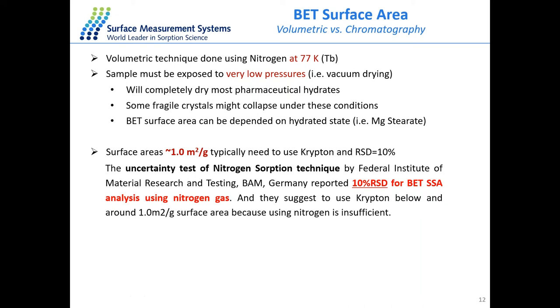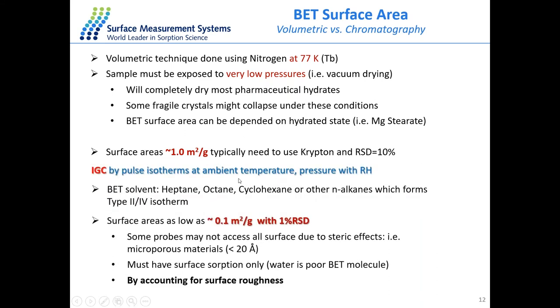With the IGC method, we perform the experiment at room temperature as well as ambient pressure, which keeps the original nature of the sample without any damage. So the value from the IGC technique is more accurate in this case compared to the volumetric technique. Another limitation of nitrogen sorption is that with small surface area material, it will give a very large variation. In this case, we need to use krypton as the probe molecule rather than nitrogen. With the IGC method, we use organic vapors, and we can determine as low as 0.1, still with 1% RSD values. That means IGC is more accurate, especially for low surface area materials.